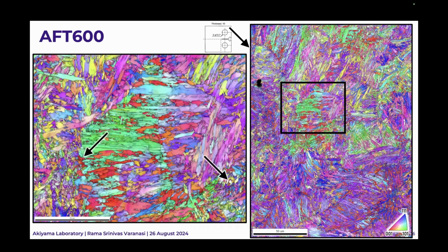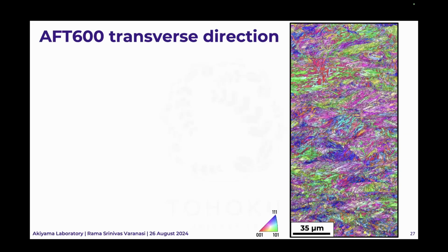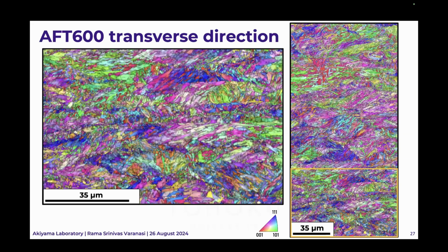But very interestingly, we start seeing these small grains. I'm not sure if you see. We ideally don't expect this because the Ausforming temperature is much lower than the recrystallization temperature. One hypothesis is that the temperature which we measure before Ausforming is on the surface using the thermocouple. It is likely that at the center of the specimen, the temperature is much higher and we see some recrystallization happening. Now, on the transverse direction, we see this pancake morphology. Again, we see these small grains suggesting some recrystallization.